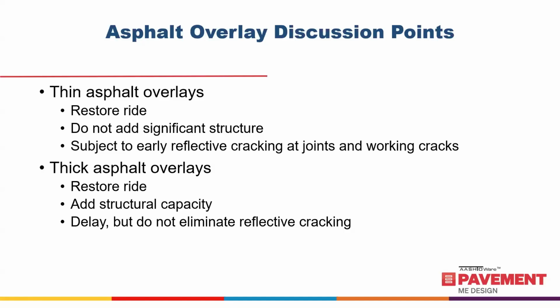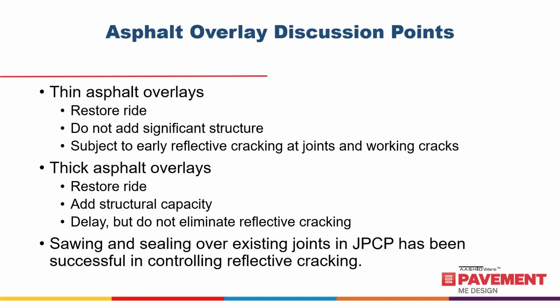Again, from experience, I've noticed that SMAs don't necessarily prevent a reflective crack from showing through, but it does lessen the severity of the crack. So some of these surface mixes are effective at mitigating either the amount or the severity of reflective cracks. And one solution that has worked pretty well is anticipating the crack by sawing and sealing over the joints, cracks or joints in jointed plain concrete. And that way you're going to force the reflective crack to basically meet where you sawed it and sealed it. So you're going to have a nice, neat sealed joint in the asphalt across the pavement, and you're not going to have a ragged joint to have to deal with.